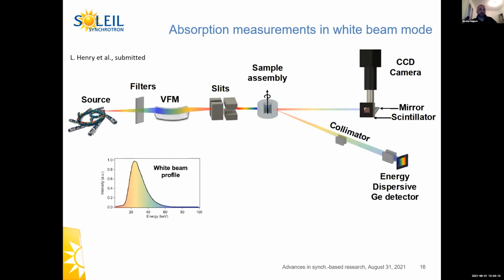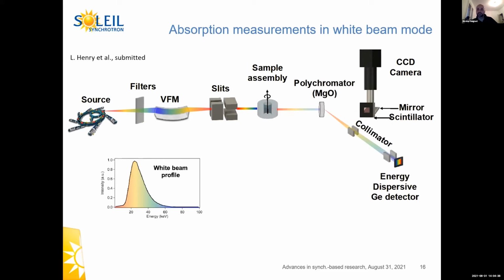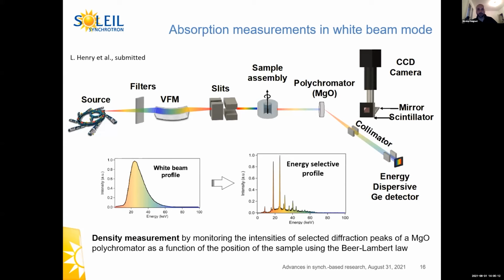But as you remember, on this beamline we don't use the monochromatic beam. We use the white beam or pink beam. And we want to keep this white beam and pink beam to keep the techniques I've just presented before, the high-speed tomography and the CSR X-ray diffraction technique. So we had to find another way to do these kinds of measurements. The idea here is to change the configuration and put the polychromator after the sample, keep the white beam, and change the slits of the CSR diffraction system to get the diffraction pattern of the polychromator. Here, the polychromator is very simple. It's just a pellet of MgO powder, so a very, very simple object. So now the CSR system records the diffraction patterns of the polychromator, no more the sample.